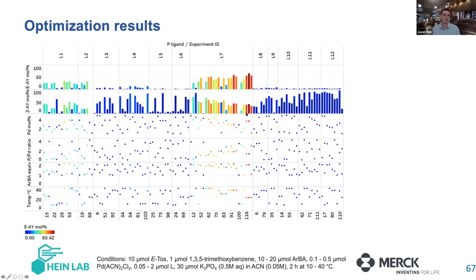So there's a little bit of extrapolative behavior we can pull out. But what we get from this is, within the same number of experiments, which would normally be like a two-plate optimization, it went through, surveyed, sampled, decided that L7 was better than the others, and then spent more of its time testing and optimizing that ligand after it down-selected the others. So it's properly guided through at this point.